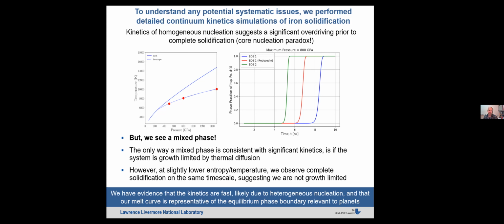But I would say the problem with this is, we made one measurement where we saw a mixed phase. What that means is that, in these experiments, it's a little bit subtle, but we shock into a liquid state, and then we compress it isentropically, and we saw a mixed phase. Now, if the physics was such that you had to overdrive it so far to observe solidification, you'd expect that once you started nucleating, you would nucleate into a completely solid state. That's what the EOS suggests.